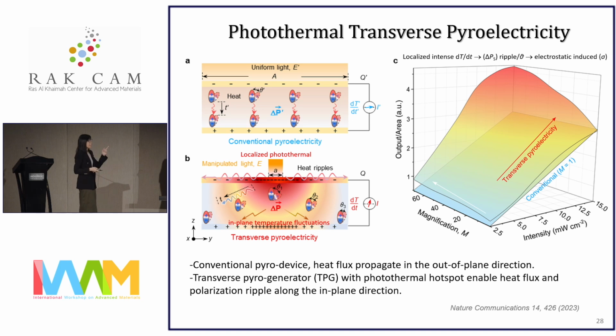In order to enhance the pyroelectricity, we have recently exploited the localized photothermal effect to induce polarization ripples, arising from the in-plane temperature fluctuation of the transverse pyroelectricity. We all know that a conventional pyro device has heat flux propagation and dissipation in the out-of-plane direction, meaning in the Z direction along the device thickness.